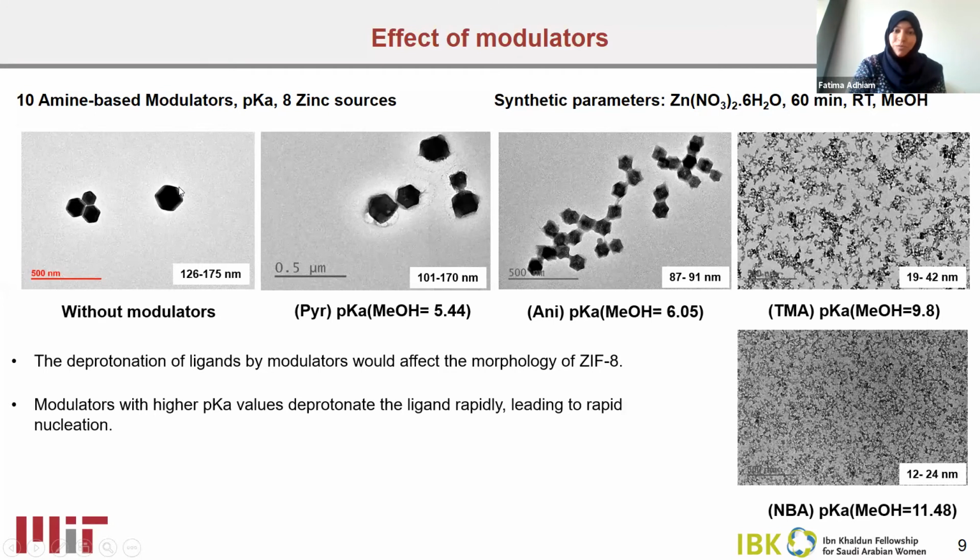comparing to this material, which forms a uniform particle shape. And actually, because these particles are apart from each other, they are not able to form this kind of connection, and hence this would affect the permeability of the material. So the uniformity in this case won't play a significant role, but the connectivity of the particles themselves would control the permeability of the material.